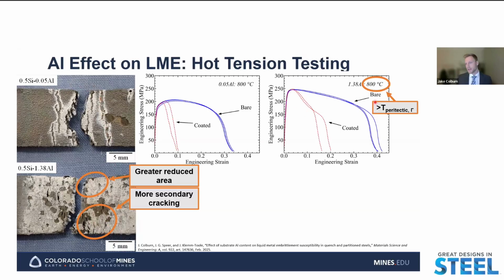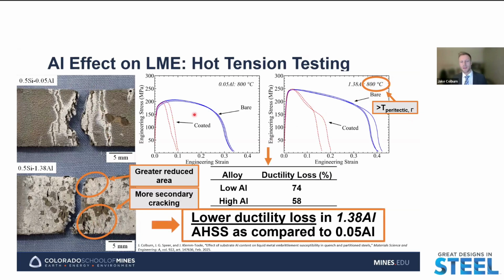And so, again, this testing was done at 800 degrees C, which is a notable temperature because we're now above the peritectic temperature for the gamma phase. So in the binary iron zinc system, we would expect that the gamma phase is not going to be stable at this test temperature. And if we compare the ductility losses between the bare and coated samples of these two alloys during the hot tension test from the stress strain curves, we see a lower ductility loss for the higher aluminum alloy, to a lower extent than what we saw when comparing our high and low silicon alloys, but still a noticeable difference in the ductility loss between these two alloys. And so we would say that the higher aluminum alloy exhibited lower ductility loss, a lower degree of embrittlement in this test.